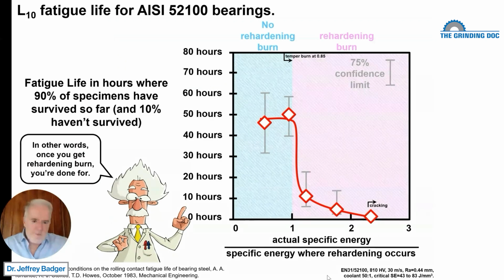What he found is, this is the fatigue life of his 52100 bearings after they've been subjected to an oscillating load. If Dr. T did not grind the material abusively, if he ground it gently, the bearing lasted about 50 hours before some fraction of those bearings failed. And then if he ground it a little bit harder, he still got about 50 hours of life out of that bearing. But then when he ground it at such an abusive condition that he got rehardening burn.